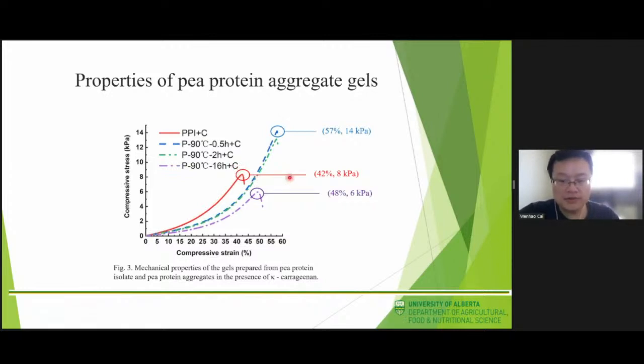Heating a mixture of untreated pea protein and κ-carrageenan at 90 degrees for half an hour led to a gel with compressive strength of around 8 kPa, and the gel was broken at the compressive strain of around 42%. The formation of good gels by combining a small amount of κ-carrageenan with untreated pea protein could be attributed to the formation of phase separation gels. The incompatibility between pea protein and κ-carrageenan was increased due to the heat-induced pea protein unfolding. This led to an increased apparent protein concentration when it was excluded from the space occupied by the polysaccharide, so it promoted protein interaction to develop a strong gel network.